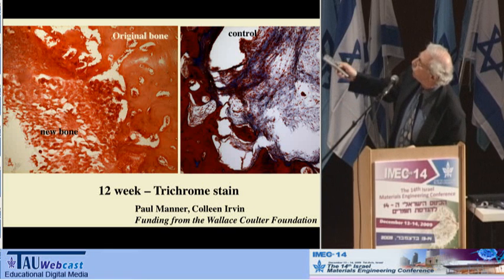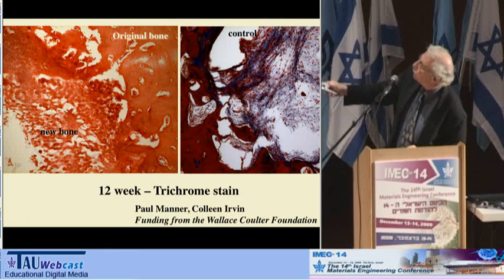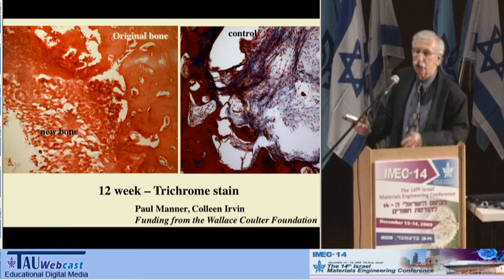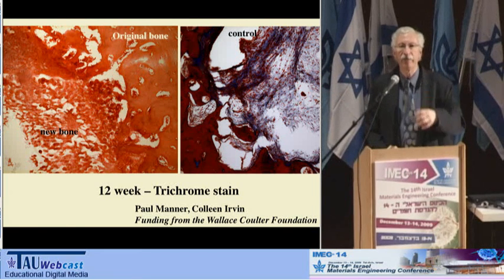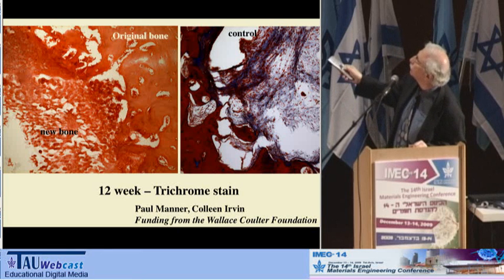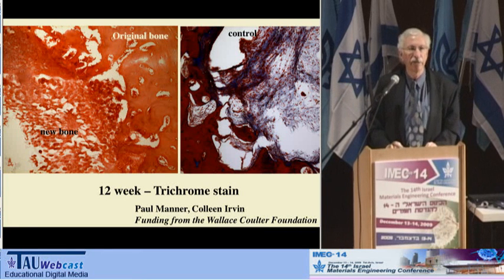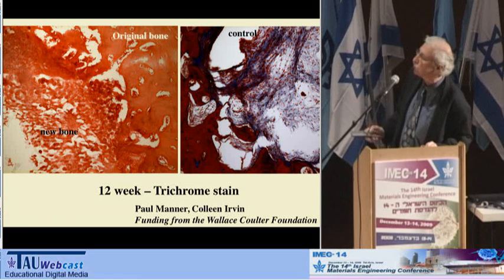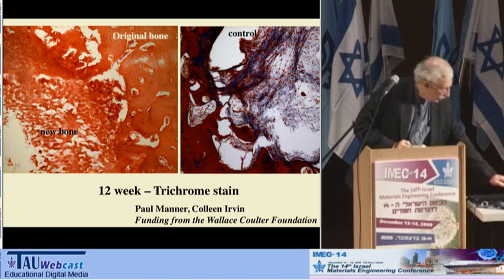this is what the original bone looks like, and what he found was new bone just growing into this sphere-templated structure. This is the control, which was just a divot, a hole drilled in the bone and allowed to fill with clot. And basically, there's nothing there. There's no reconstruction, essentially no reconstruction at all.